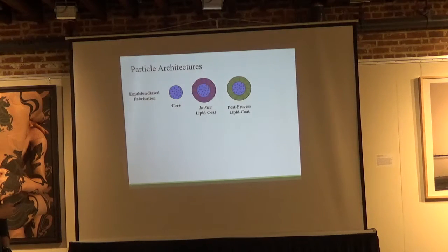So here we have different formulations that we have done in the past, emulsion-based, where you can create a polymer matrix core that has drug, denoted in red, through it. And we can also do an in-situ lipid coating process, or do a post-process lipid coat on these particles to modulate release. And you can also look at electrosprayed formulations.